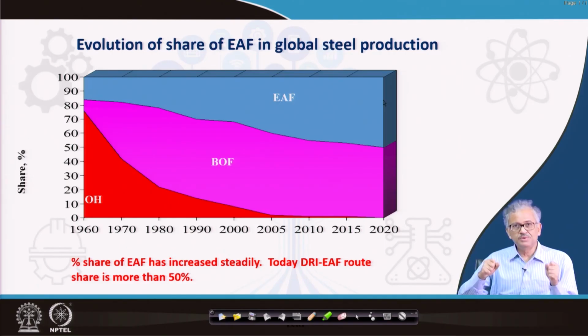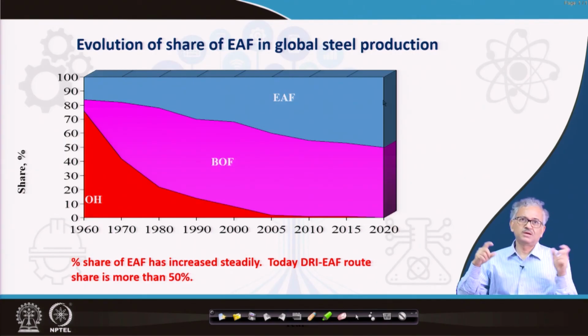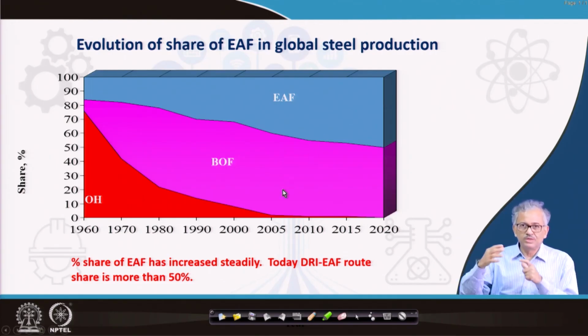So, as a result, solid metallics are increasing. If you increase the solid metallics, then you need an electric arc furnace, because the BOF, basic oxygen furnace, has a limitation of taking solid charge as a coolant. It cannot take more than 25%, but EAF can take any proportion. It can take hot metal, scrap, DRI in any proportion, because it has this external source of heating. So, if the solid charge goes beyond 50%, it is not a problem.